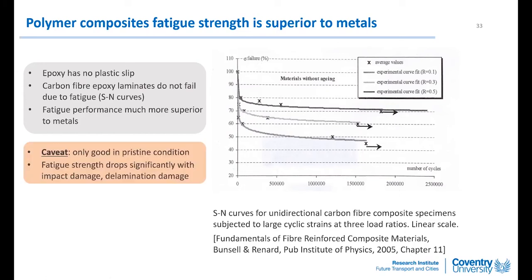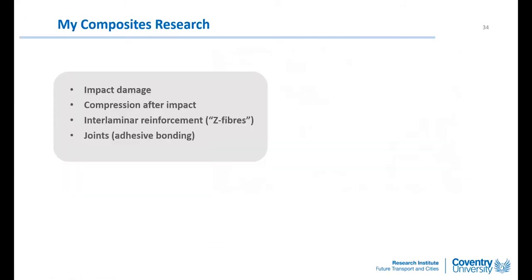However, there is a caveat. Only if composites in good condition, in pristine condition. Fatigue strength will drop significantly if we have impact damage, if there is a delamination, if the manufacturer has imperfection in the laminate, they call it manufacturing defects. So that has been my research for the last 30 years.